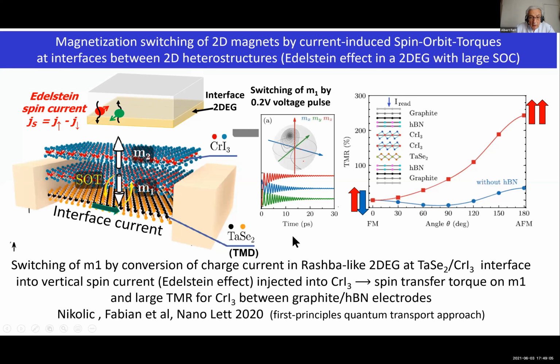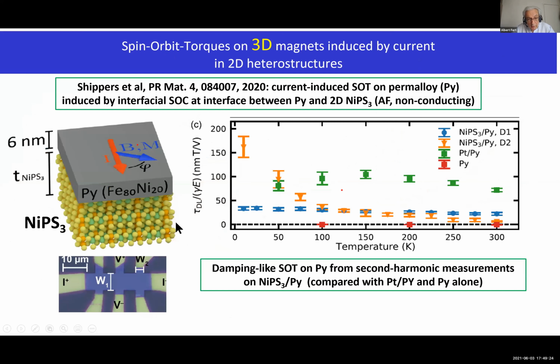Okay, so in fact, I did not find a lot of clear experimental results except this theoretical paper on this problem of the exploitation of the 2D electron gas, the spin orbit coupling and the Edelstein effect in a 2D electron gas. The only one I could find is this one. So it uses 2D magnets based on nickel PS3, which is an insulating layer. On the top, there is a permalloy layer. And so with a current at the interface, the interpretation of this result is that the current in this 2D electron gas at the interface generates by Edelstein effect a spin current into permalloy that can exert a torque on the magnetization of permalloy.